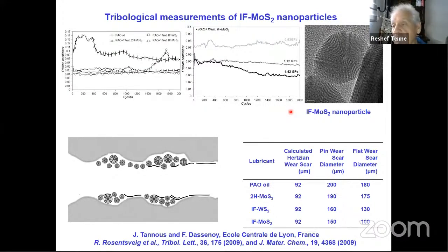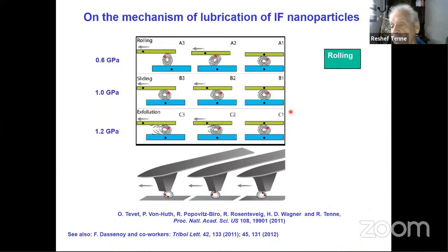So this is just a glimpse of huge studies that we and others have done, and this is now technologically available. There are quite a number of companies that are using these lubricants, which started in my laboratory. We have studied the mechanism of lubrication, which is quite different from the known lubrication mechanism. In the case of molybdenum disulfide, it is well known that it lubricates by shearing the layers on top of each other. But here, because you have a closed structure, they cannot shear.